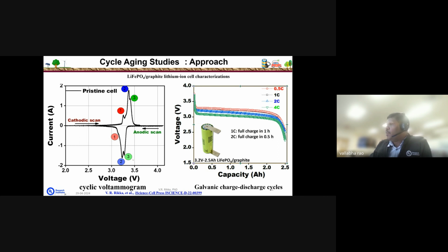That's why whenever we perform this kind of cyclic voltammetry analysis, we can identify whether reducing the operating voltage even below 2.5 volts puts the cell under an aging condition or not. In our case, no degradation mechanisms occurred even at the lower operating voltages. So we have included this limiting factor for high charge rate performance, which enables us to utilize the total available energy density from the lithium cell.